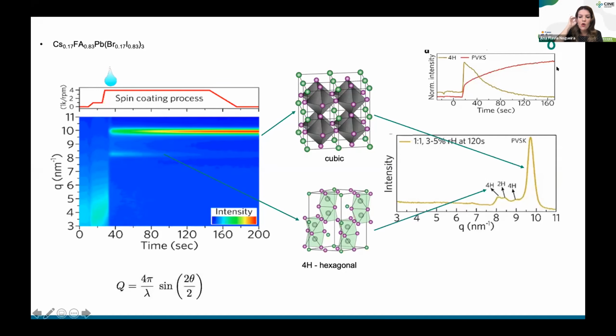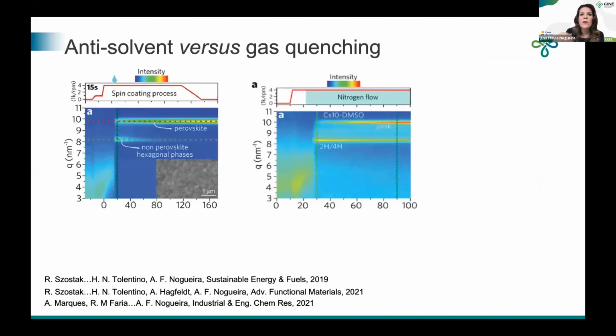So what happens now when you compare this with the gas quenching, when you use the nitrogen flux? This is the data that I showed you before here on the left. This is the new data on the right. You see here that in both cases, we are forming the cubic perovskite. Also, we are forming the hexagonal phases.